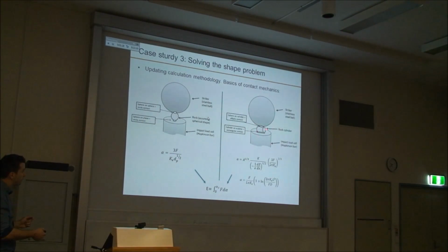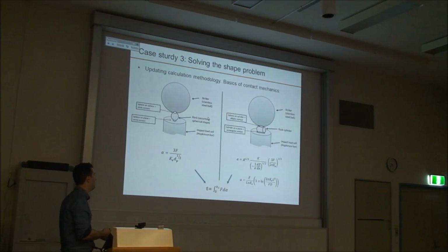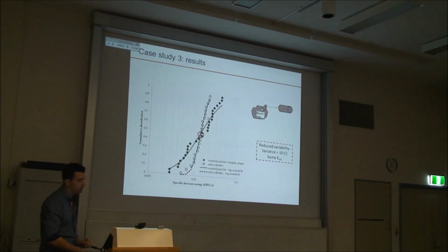With the cylindrical shape, the deformation of each of the areas here and there are actually described by other theories that have been derived and that are much more complex. But so far, the impact load cell was only used with the equations on the left, never with those on the right. So I had to rederive all the equations. And what I did is I simply used the calculation of energy and force, which is the integral of the force versus deformation, like the area under the stress-strain curve, and used those parameters to recalculate the actual breakage parameters, the fracture energy, the stiffness, etc.